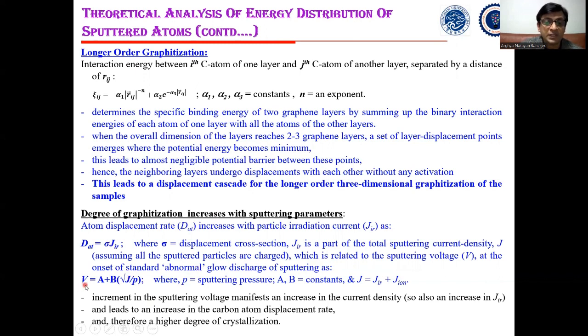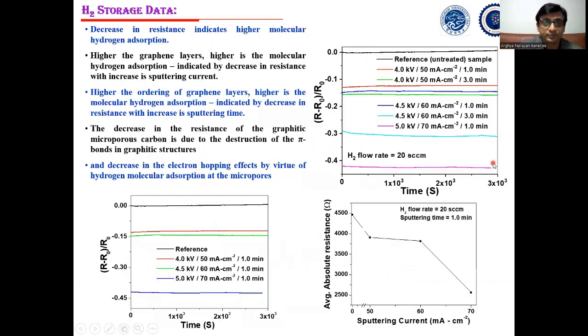You can see that when we increase the sputtering voltage, the sputtering current is increasing, which is also increasing the graphitization to increase the number of graphene layers as well as improve the ordering.